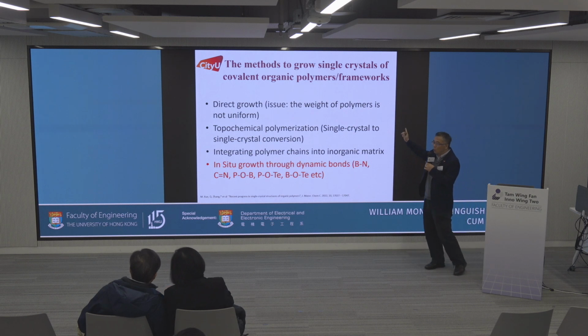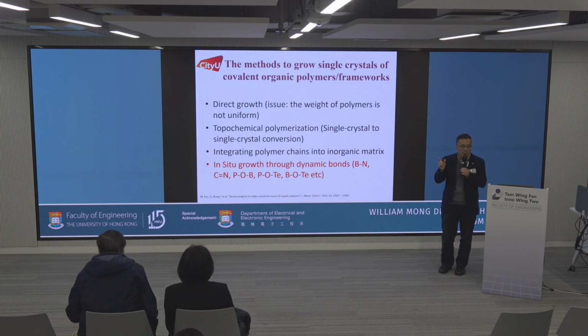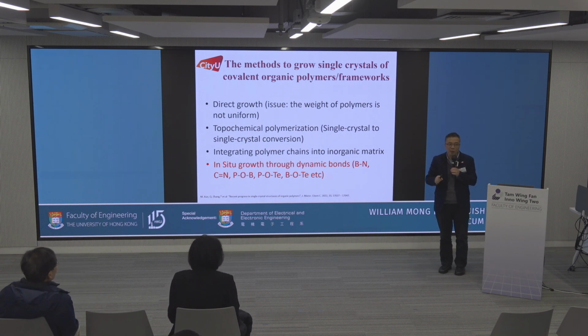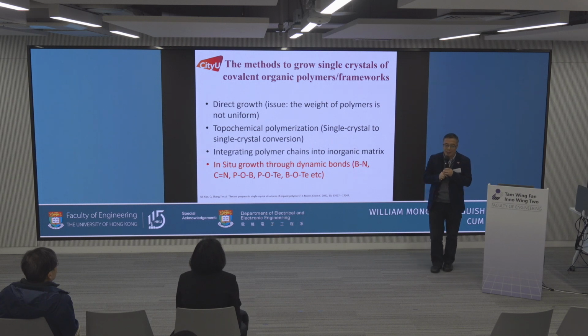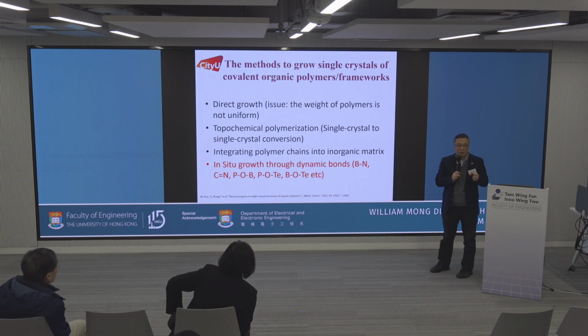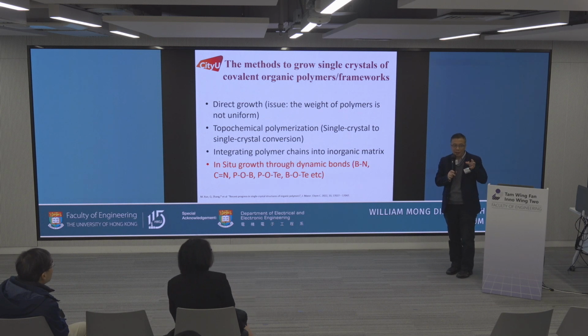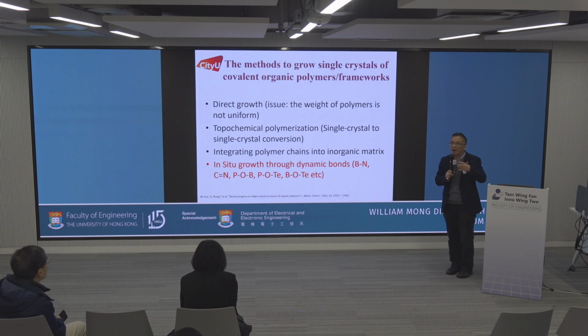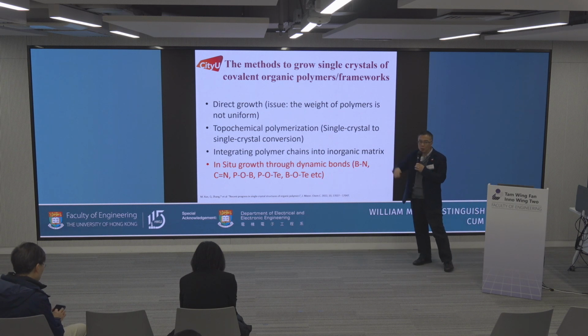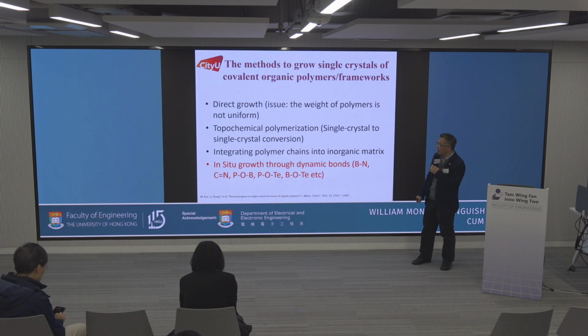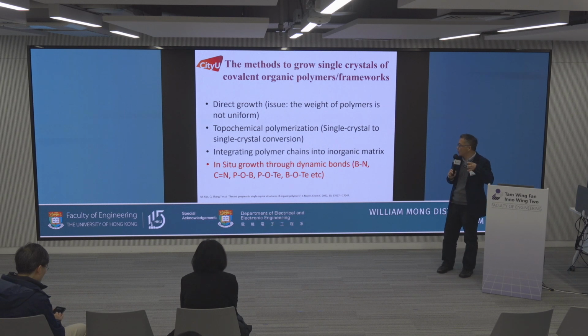However, this method looks very simple, but it is very difficult. The reason is that when we synthesize the polymer, the polymer chain should be uniform. Otherwise, the polymer is a mixture, okay? The second method is topochemical polymerization. This method requires that we make the polymer precursor first, and then we grow a single crystal of the precursor. Then this precursor can be converted into the polymer crystal through heating, light, or pressure. So it is pretty much based on converting a single crystal of monomers to a single crystal of polymers by external stimulation.